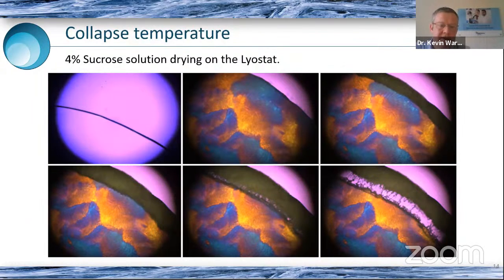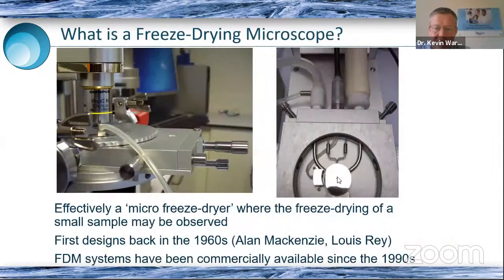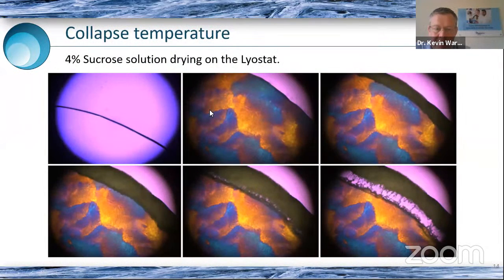So here on the top left, we can see our liquid sample that we've put onto that silver block, and you can see the circle around it is the aperture in the block that you saw on the previous diagram. So the small hole in the center of the block is what we're now looking through. The top middle photo shows our frozen sucrose solution. And we're using what we call a first order red filter in order to artificially color the ice crystals according to the direction that they're facing. And you can see in the third picture on the top right, we've just applied a vacuum, and our sample is now freeze drying from the edge of the sample inwards, and we've got a band of dried structure that